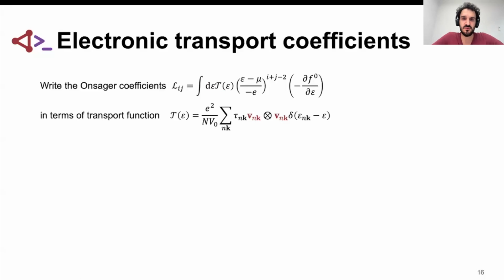The Onsager coefficients can be written in this very short form that depends on the transport function, which is simply Brillouin zone integral of the group velocities with a delta function and relaxation time for a particular electronic state. This transport distribution function is a convolution in energy with the derivative of the Fermi occupation energy. Depending on which little element of the 2x2 matrix we are looking at, we get a weighting function.